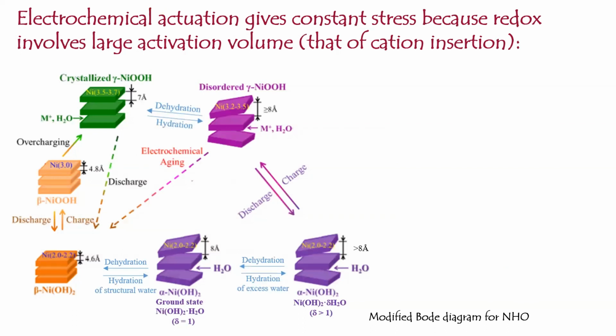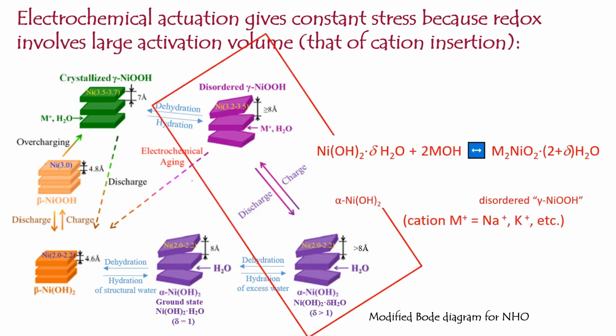Why? This is the so-called Bode diagram for this well-known material. So many different phases, okay? But for electrochemical actuation, we simply make use of the transition between these two phases. So the hydroxide transforming into the oxyhydroxide, and that involves insertion of some cations in the electrolyte. So it depends on what electrolyte you're using. If you use sodium hydroxide, then the cation would be sodium. If you use potassium hydroxide, then the cation would be potassium.